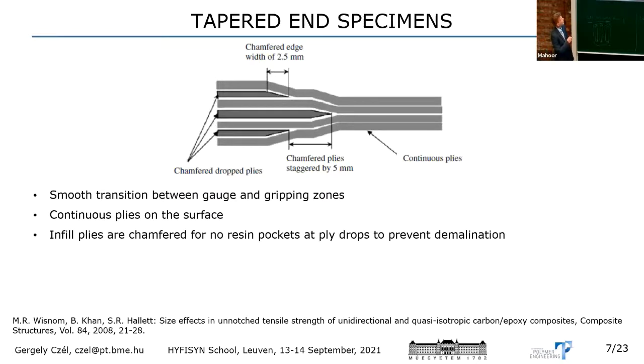And another key feature is that these infill plies are chamfered, so that there are not too big resin pockets at their end, which can reduce the possibility of delaminations starting from those resin pockets. So this is a clever concept.